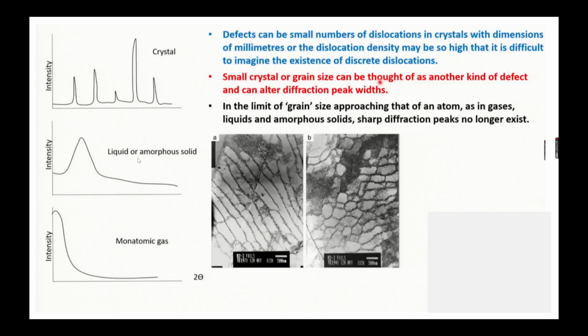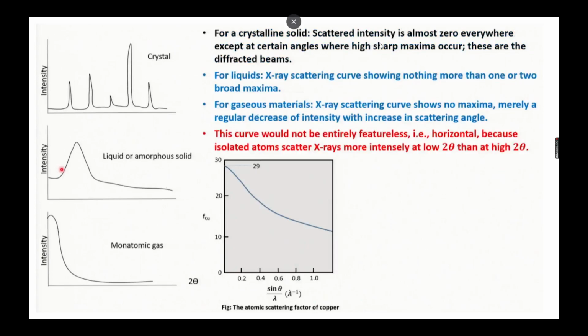In the XRD lectures we have seen how an amorphous material or a liquid gives its XRD pattern. If you have a crystalline material, you will get sharp intensity peaks, and if it is amorphous, you will get a broader peak. For a gas you will get this kind of a peak. For a crystalline solid, the scattered intensity is almost zero everywhere except at certain angles where high sharp maxima occur. These are the diffracted beams. In the case of an amorphous or liquid sample, the X-ray scattering curve shows nothing more than one or two broad maxima.